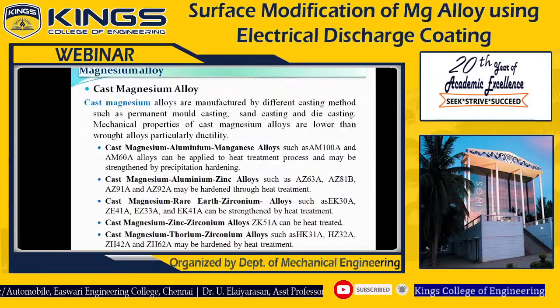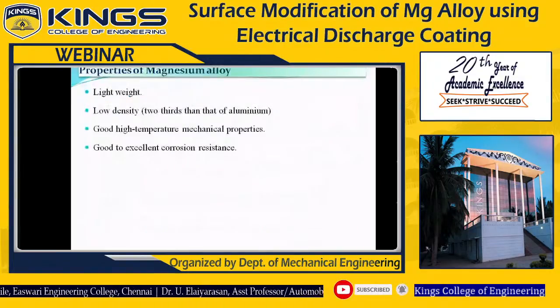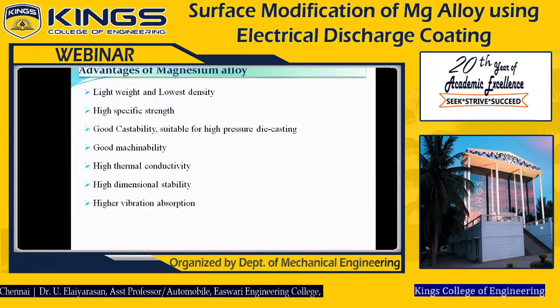Some zinc zirconium alloys, cast magnesium and thorium zirconium alloys as well. Properties of magnesium alloy: I have given 4 properties. Lightweight, low density, about 2/3 that of aluminum; good high temperature resistance and mechanical property; very good to excellent corrosion resistance. One of the main drawbacks of this magnesium alloy is wear resistance only. Advantages of magnesium alloy: lightweight and lowest density, high specific strength, good castability, suitable for high pressure die casting, good machinability, high thermal conductivity, high dimensional stability, and higher vibration absorption. These are all the main advantages of the magnesium alloys.